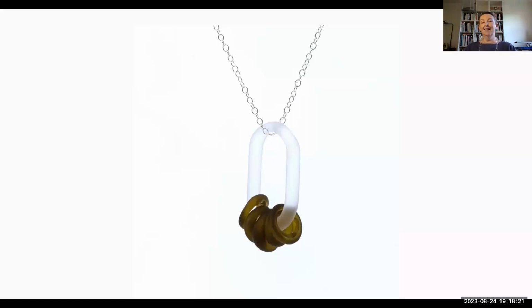And it's that thing that properly made glass is really strong. Yeah. But actually, backtracking slightly to the Viking skill levels again, if you look on any modern glassmaker's website, we talk endlessly about our glass is annealed to take the stress out. And what that means is when we've finished, it goes into a kiln that's digitally controlled. So it sits at certain temperatures. So you take it up to the point that the glass can relax, and all the strain that you've put into it as you've twisted it and turned it and mashed it, that all relaxes out. And then you cool it down really gently.